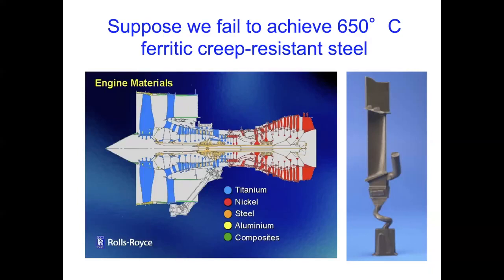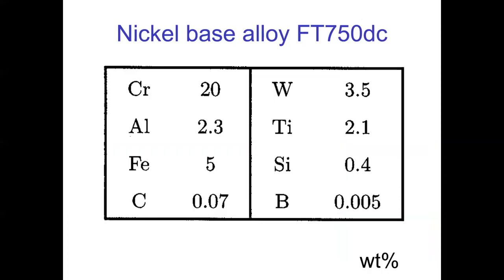Unfortunately, these alloys are incredibly expensive compared with the scale of engineering required in a power plant, right? So they contain exotic elements and so forth. So we need to down engineer these alloys because we don't need to go to 1400 degrees centigrade. We can cope with 750 degrees centigrade. So we took on a project to design a nickel alloy, which would be extremely cheap. It's still 3 times more expensive than steel, but far, far cheaper than aerospace alloys.